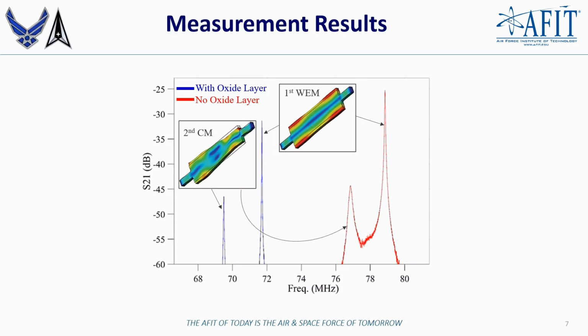The oxide layer significantly enhances the quality factor, with the resonator achieving a 6-fold improvement in the maximum quality factor compared to the version without the oxide layer. This improvement directly translates into increased sensitivity, which is critical for accurate sensing in various applications.